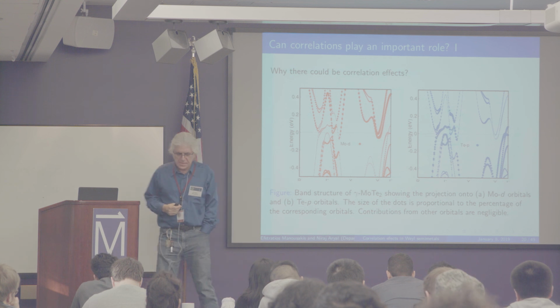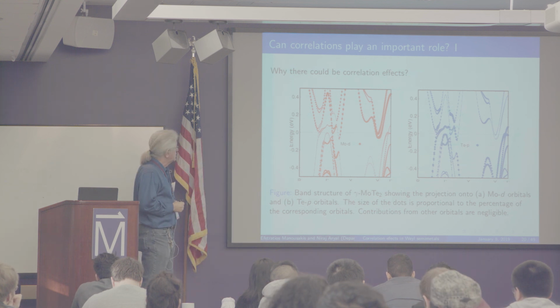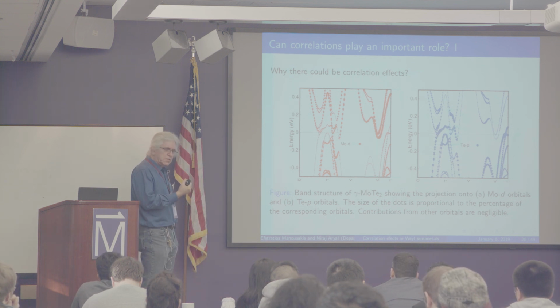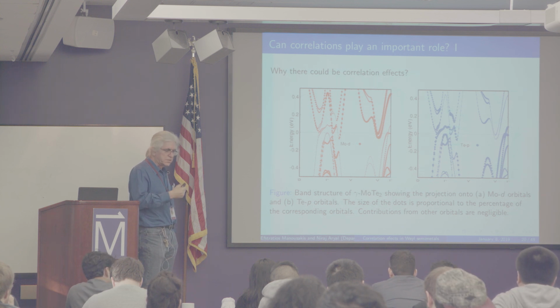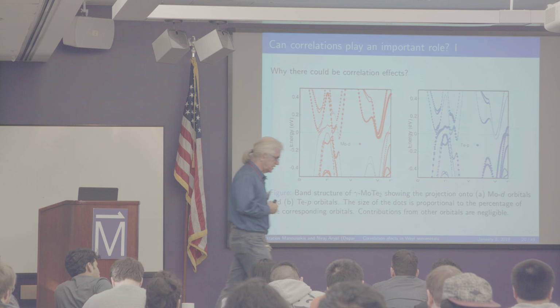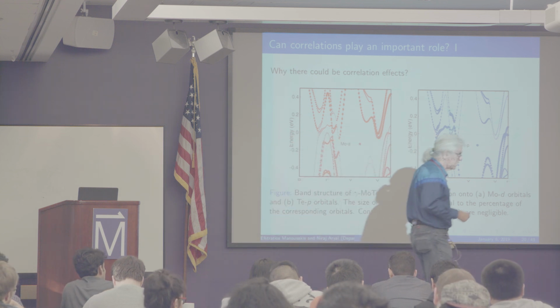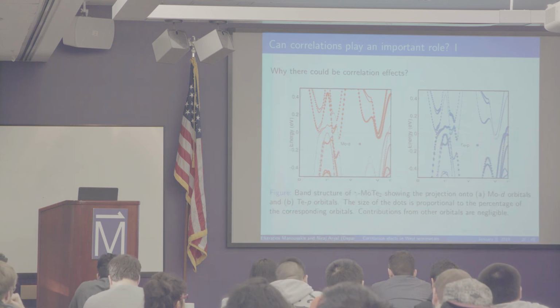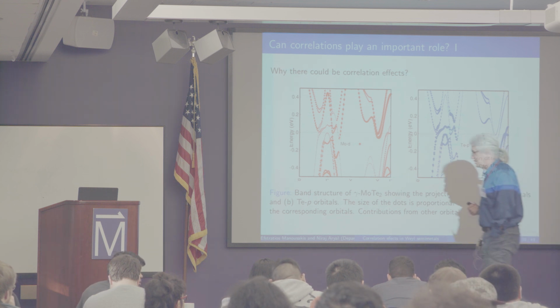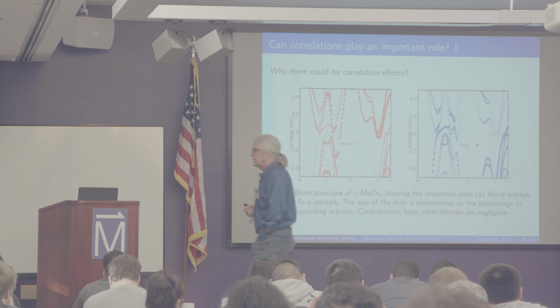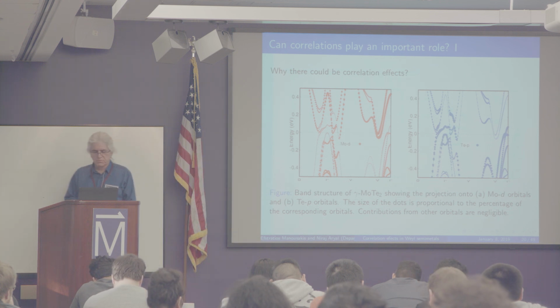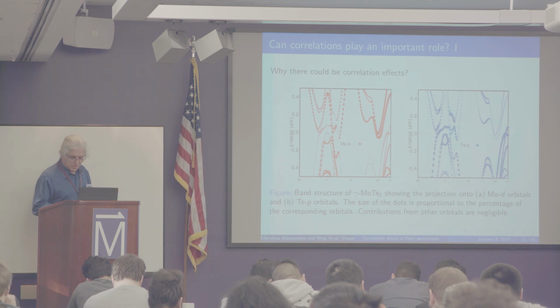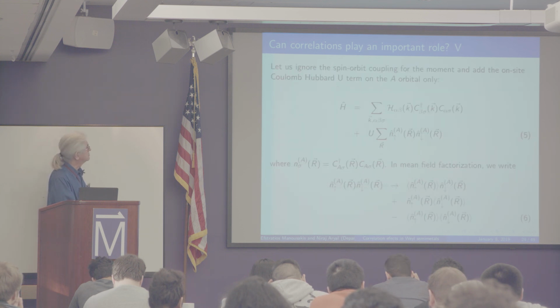It is the hybridization between D and P that gives rise to the Weyl points. It's not the spin-orbit coupling that does that. And the spin-orbit coupling, I'll discuss that in a moment. Spin-orbit coupling splits these and makes them 4 instead of 2 pairs. So let me just continue and go to the next thing.